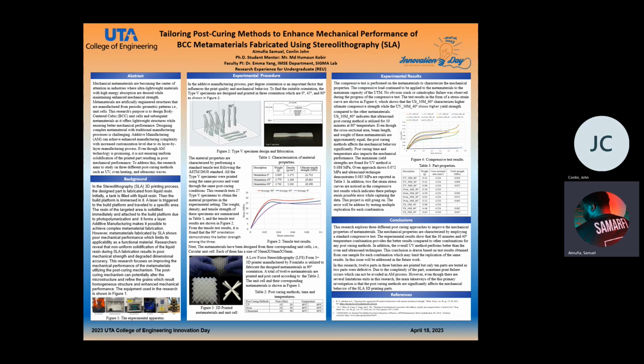Next, the metamaterials have been designed from their corresponding unit cells, i.e., the circular unit cell. Each of them has a size of 50 millimeters length, 50 millimeters width, and 50 millimeters height. A Low Force Stereolithography, LFS, Form 3 Plus 3D printer manufactured by Formlabs is utilized to fabricate the designed metamaterials at 90 degrees orientation. A total of 12 metamaterials were printed and post-cured according to Table 2, which is below. The unit cells and their corresponding metamaterials are shown in Figure 3.